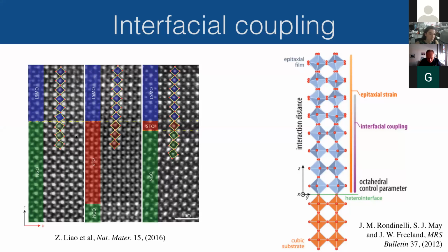because of the substrate. Then you can do cool things like put a buffer layer of strontium titanate that is this almost perfect cubic perovskite, and then you don't have such an effect. Even just one unit cell of strontium titanate, and you can kill this interface effect. So this is a super interesting field. This is a really great review article here.